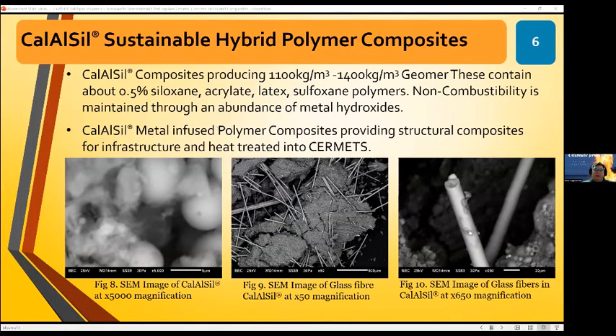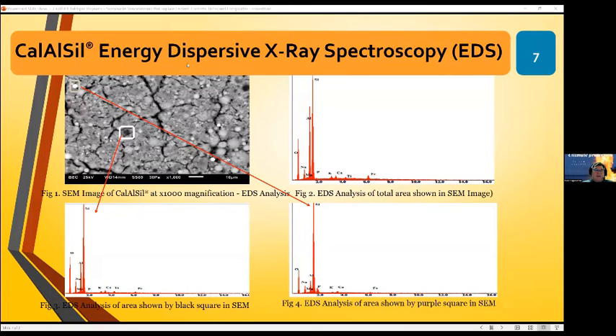Okay. So I just make the point that with the non-combustible ceramics, it's easy to infuse metal particles in them, and then burn them into high temperatures if you wanted to make a cermet, which those cermet materials have some specialist applications. So this is just an energy dispersive X-ray spectroscopy, EDS, of one of these images. This EDS on the right-hand side where my cursor is an EDX of generally the entire image. It indicates you've got oxygen, sodium, a little bit of magnesium, not much, aluminium, silica, tiny bit of potassium, calcium, titanium, and a bit of iron. Now those components all come from the fly ash that's in the mixture. The aluminosilicate is from the fly ash, and I also have particles of aluminium oxide, silicon dioxide.